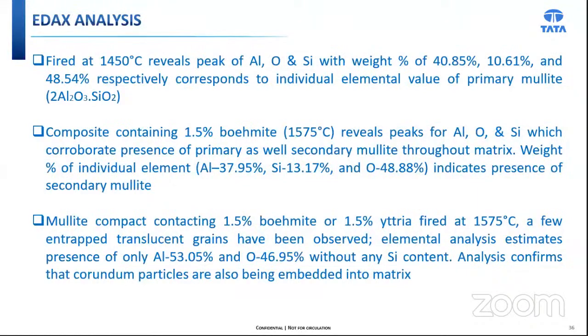Now coming to the EDX analysis, the EDX analysis of mullite and mullite-based composite fired at 1450 revealed the peaks of aluminum, oxygen, and silicon with a weight percentage of 40.85, 10.61 and 48.54 respectively. It reveals that the components closely correspond to the individual elements like primary mullite. Also, at 1575 degrees centigrade, the peaks observed contain aluminum, oxygen, and silicon, which corroborate the presence of the primary as well as the secondary mullite throughout the matrix.